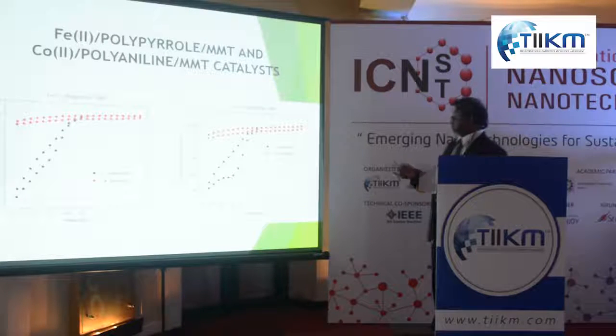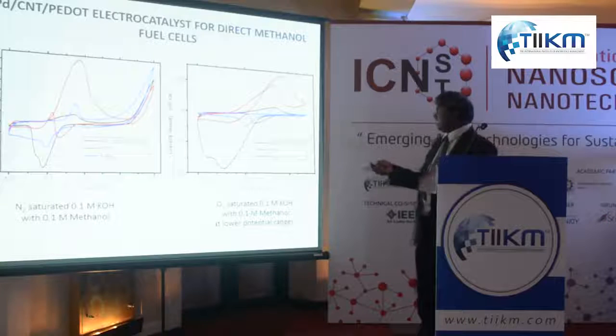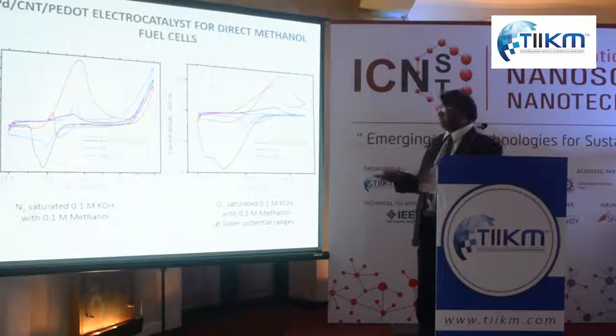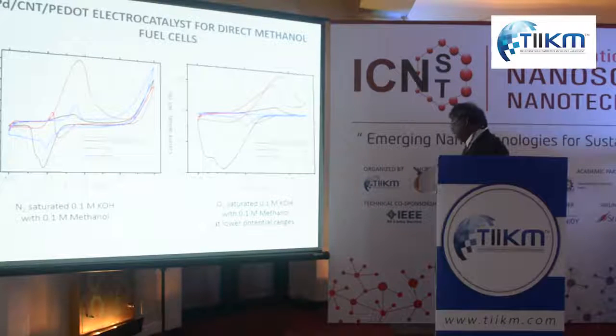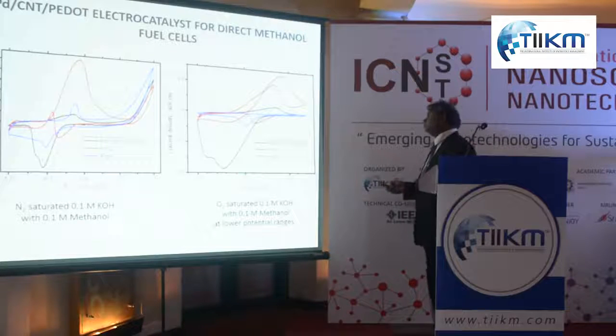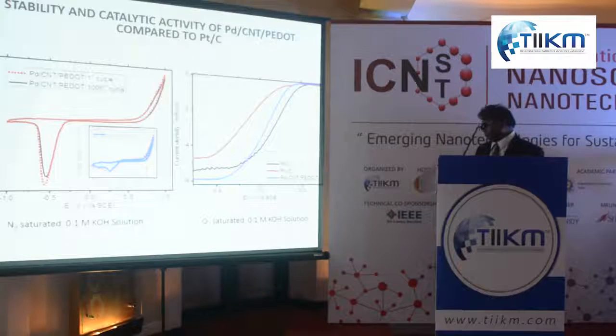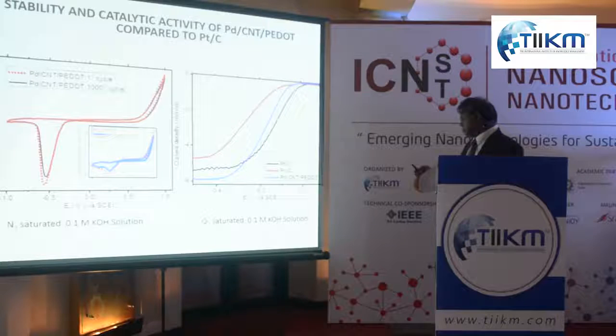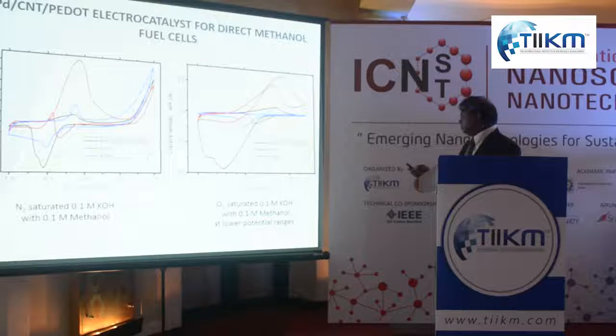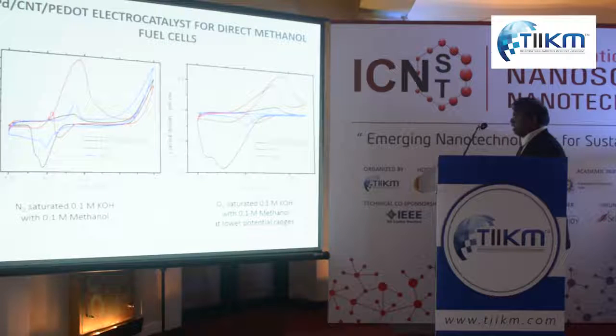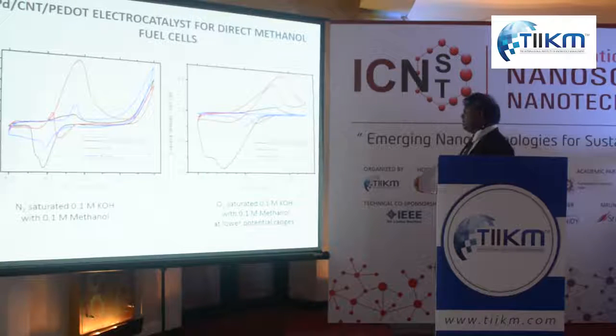And of course, we worked on most of these catalysts, 19 such different combinations, and we also compared a palladium carbon nanotube PEDOT system, a platinum carbon system, and a palladium carbon system. You see this palladium carbon nanotube PEDOT is much better than both platinum carbon and palladium carbon.